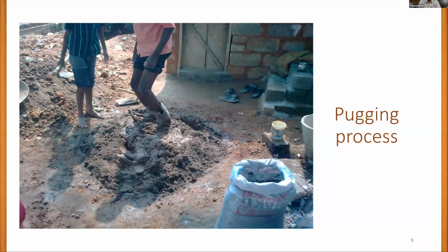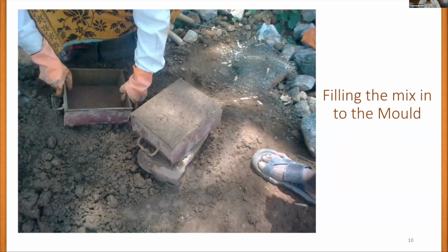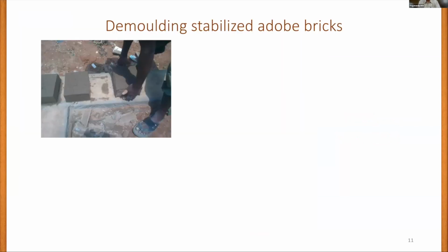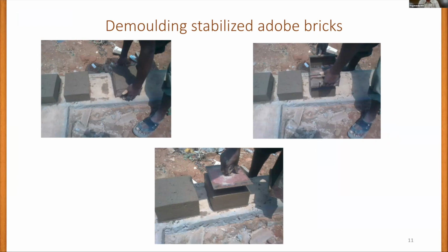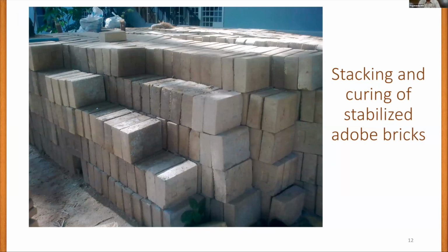And then you can choose the mold sizes and the type of mold. You can fill the mold properly without any air gaps. And then you can take it out and demold it immediately. That is what is happening here. This is a modified, improved mold that we have for stabilized adobe making, wherein it has a bottom plate also. So you get a very good shape of the block, and demolding is easier. Once it is demolded, you leave it for a day and then you stack it for curing. That is how it happens. Wherever you put lime and cement, you need to cure it for 28 days. Curing can be done by just sprinkling water once you stack it like this.